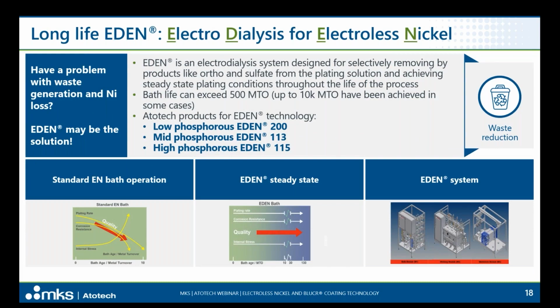While the traditional electroless nickel technology offers EN processes with a limited bath life of 8 to 10 MTO, the use of Eden technology increases the bath life up to 10,000 MTO. Why? Because Eden is an electrodialysis system designed for selectively removing byproducts like orthophosphate and sulfate from the plating solution, and so we can achieve a steady state plating condition, and we can plate until 10,000 MTO.